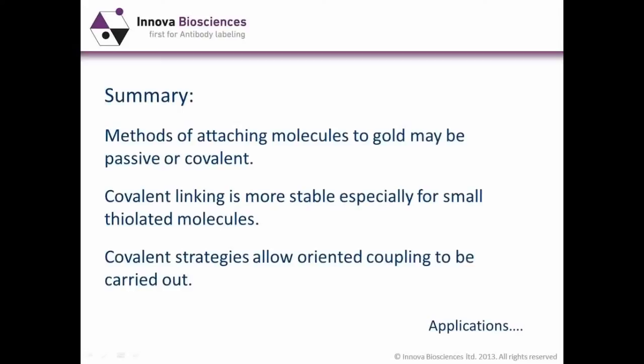Okay, just to summarize this section, methods of attaching molecules to gold may be passive or covalent. Both have their place. Covalent linking is more stable, especially for small thiolated molecules. And covalent strategies allow oriented coupling to be carried out. This is not possible with passive coating where the orientation is random.